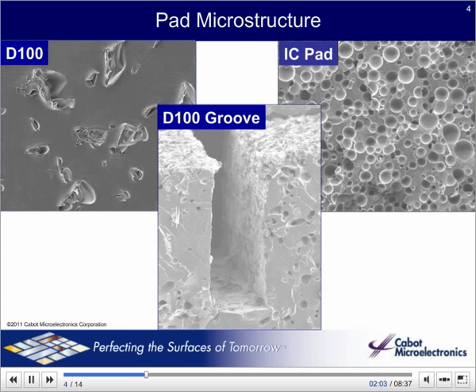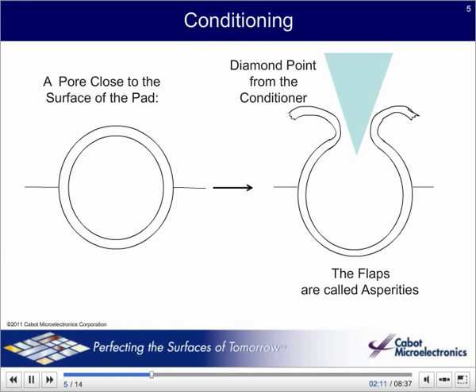We deliberately pop the bubbles on the surface of the pad using a disc of sharp diamonds called a conditioner. When the pores are scored with the diamond conditioner disc, a number of them pop open, and the tongue-like flaps that form are called asperities. These stick out from the surface of the pad and are what makes direct contact with the wafer during the polishing process. Usually only about 0.1% of the area of the pad actually touches the wafer. You can see why the size and shape and hardness of the pores are so important, because this is where the rubber meets the road.